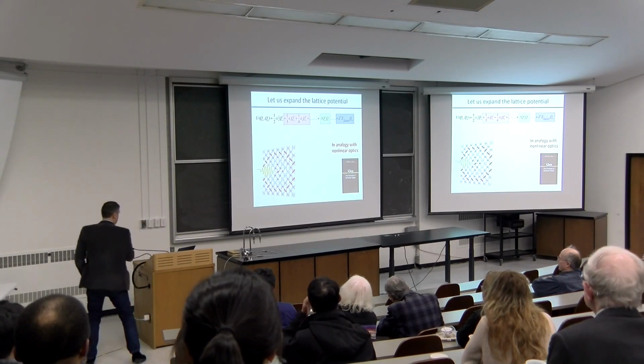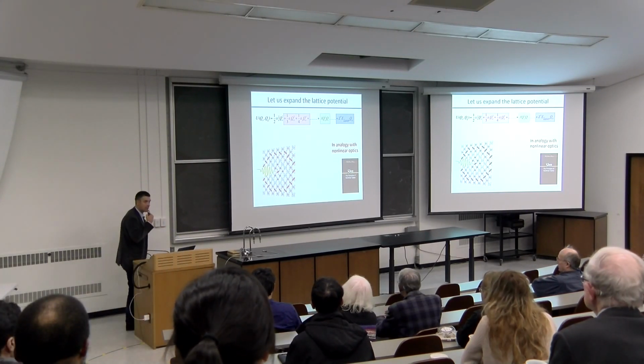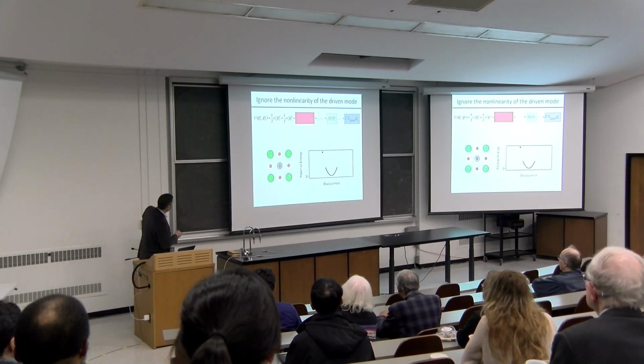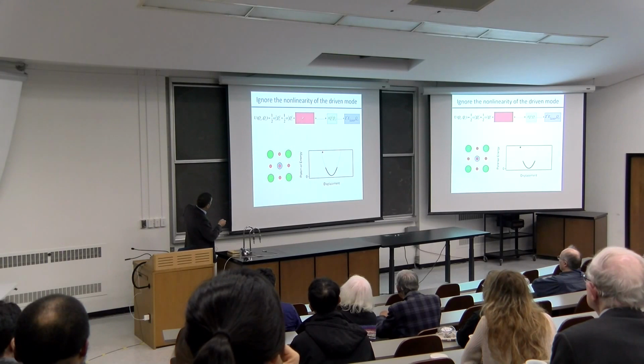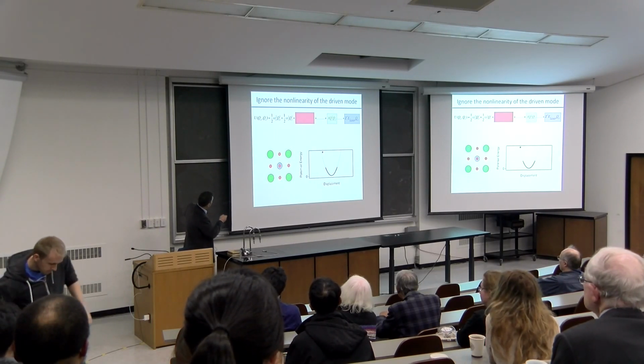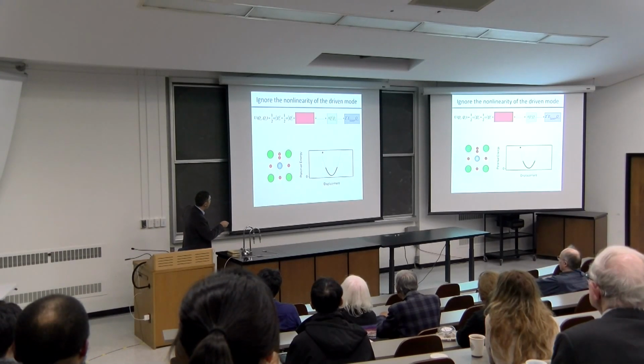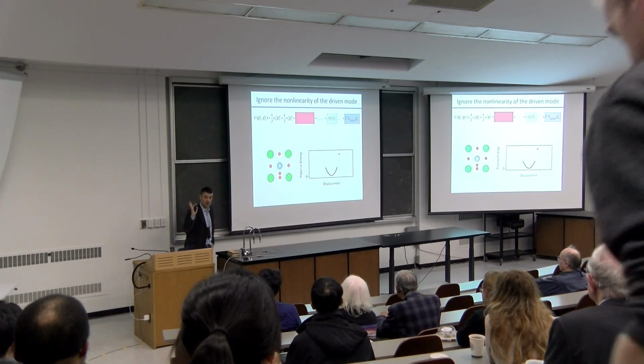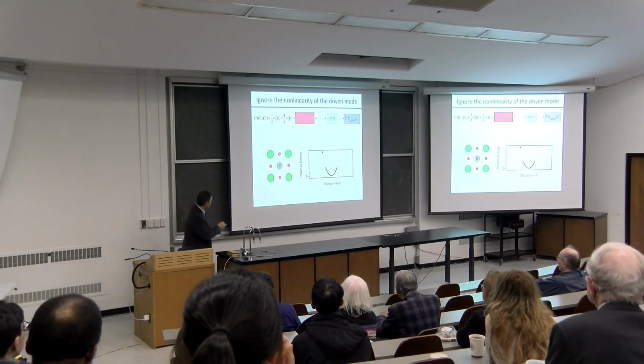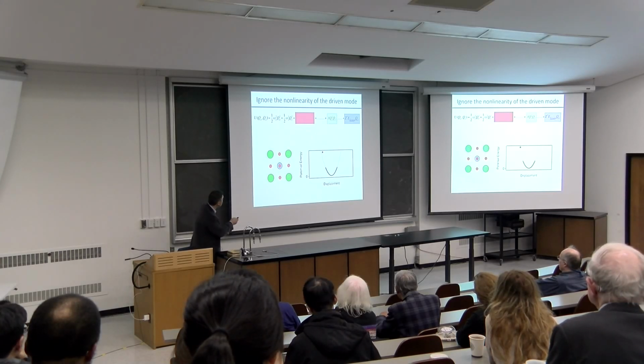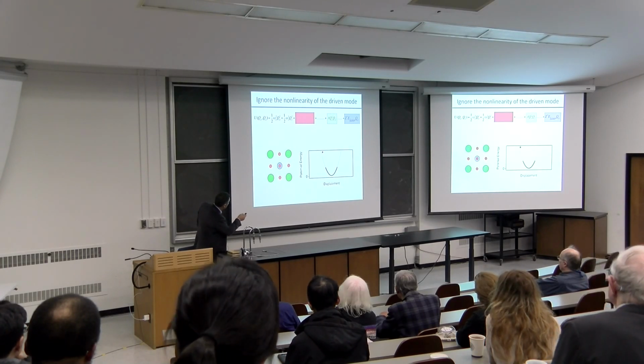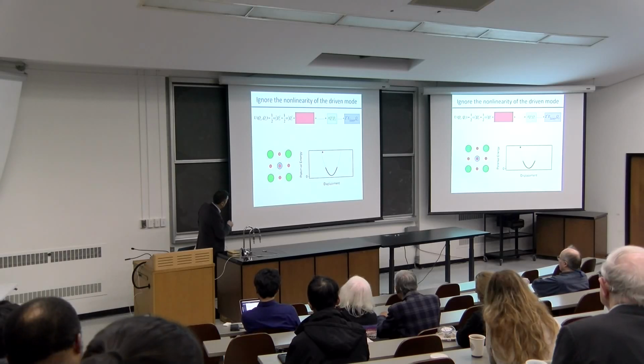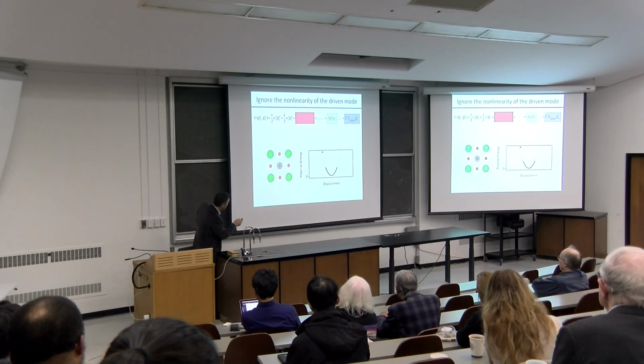Okay? And just to make an example of why this is powerful, I am first going to completely ignore the nonlinearity of the driven mode. So I take this mode, I couple light into it, and I shake it to very large amplitude, but I'm imagining that although the amplitude is very large, the mode is fully harmonic. Of course, this is not true, and so the only thing, sorry, I don't want to make you dizzy here, the only thing that I need to worry about is now how this large amplitude mode couples to the other phonon. So this is the lowest order coupling that my driven mode will achieve on other modes that are in linear response are normal to it.